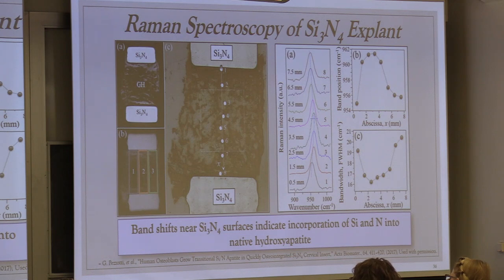So here's the graft hole, here's the silicon nitride source, sectioning this in half, and looking at the implant and looking at various positions along the implant to see, okay, are there chemical or structural changes that are taking place to the hydroxyapatite? And yes, there is. You can see that as you look at the Raman spectra, you can actually see a Raman spectra that is being depressed to a lower wave number close to the implant, and it goes out and then comes back in as you go across the implant. You can see that here in the other two graphs as well.